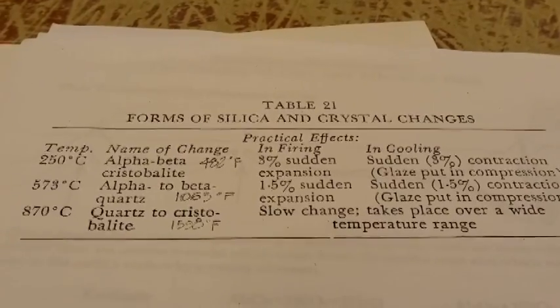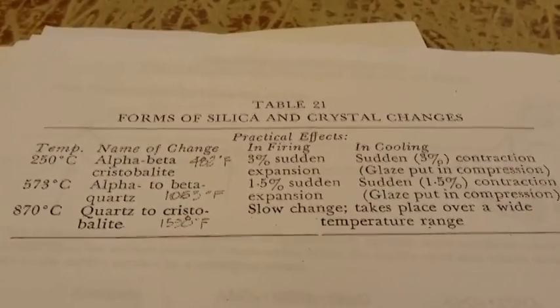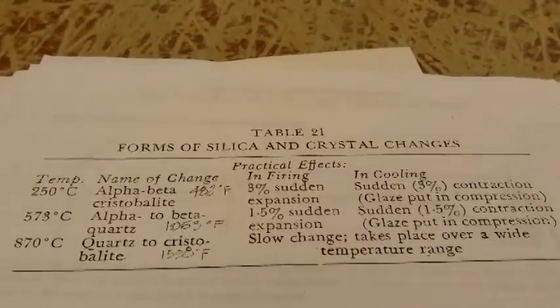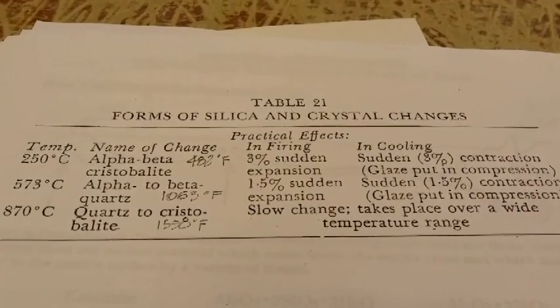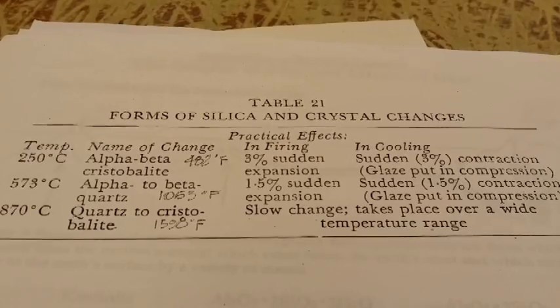I've mentioned to you that things expand when they get warm, and things shrink as they cool, except for lithium compounds. On the left at the top, it's the alpha-beta cristobalite change at about 250 centigrade or 482 Fahrenheit. As the piece heats up, the crystalline structure changes in orientation, and it yields an almost instantaneous 3% expansion in physical size. Wow, that's big. Or during the cooling phase, a 3% contraction. 573 centigrade, or 1063 Fahrenheit, is a 1.5% expansion or contraction.